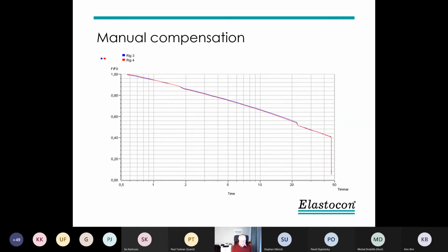In many measurements, you have errors, but if you know about the errors, then you can compensate for them. The error we have mainly is the stiffness of the load cell, and also the stiffness of the whole test rig, but especially the load cell. The load cell is being deformed. It's the way a load cell is measuring the force. So it's getting a little shorter when we compress something. And when the rubber then relaxes, the load cell will spring out, because it's in fact a very stiff spring, and compress the rubber a little more, and then we get an error.